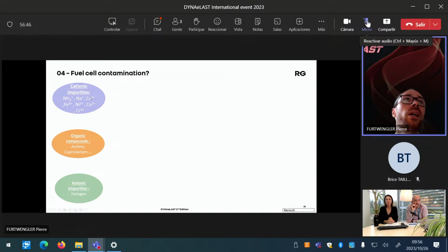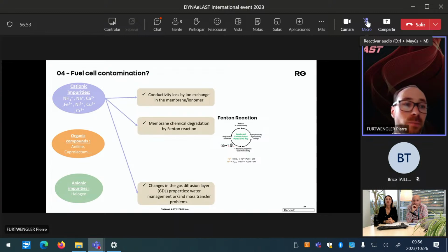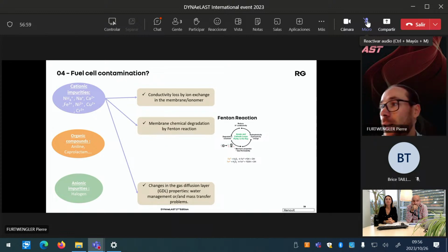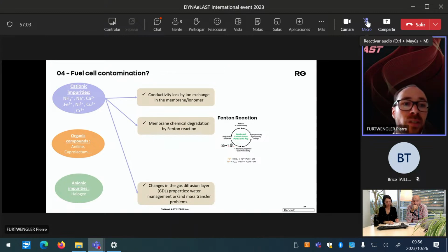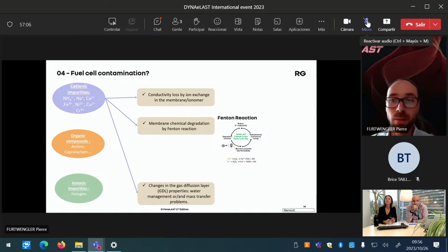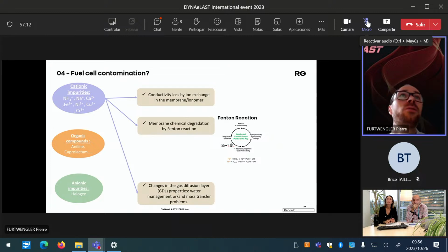Cationic impurities are mainly ions, extracted by leaching from the compound. Why are they quite bad for us? Because one of the main catalysts of the fuel cell is platinum. So if this metallic catalyst is poisoned by one of the cations, it will not work for the fuel cell. It will work to create another reaction or whatever we want with these impurities. So it basically decreases the yield of the fuel cell. This cation can also interact with the membrane, which is a polymeric membrane inside of the fuel cell currently. So we can have interaction with the porosity of the membrane and decrease the efficiency one more time.